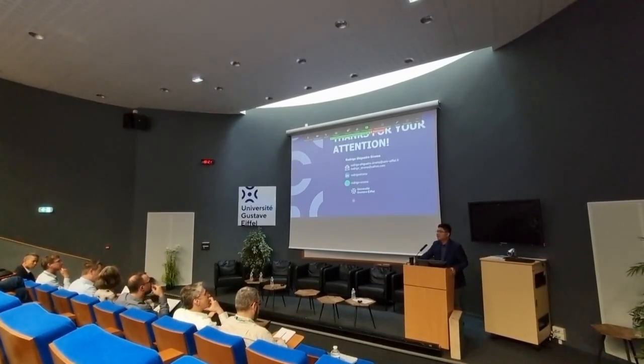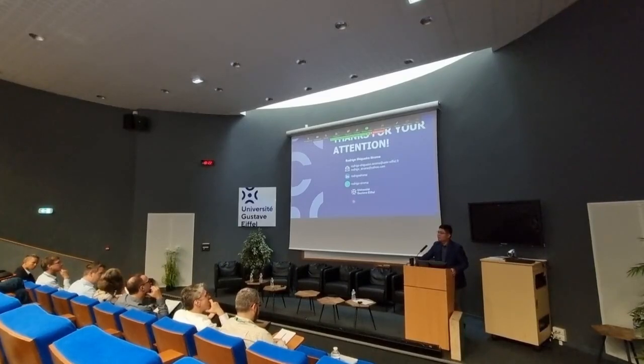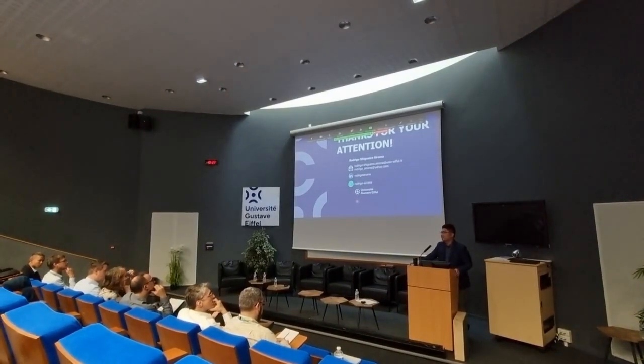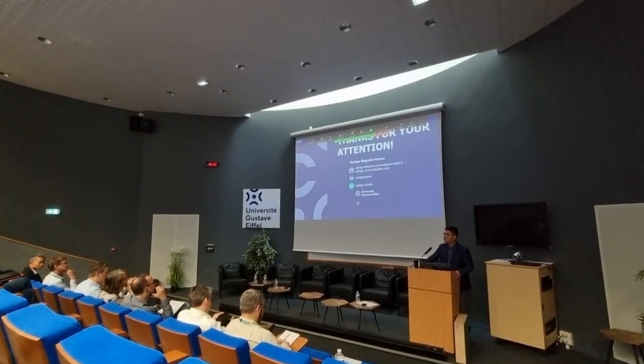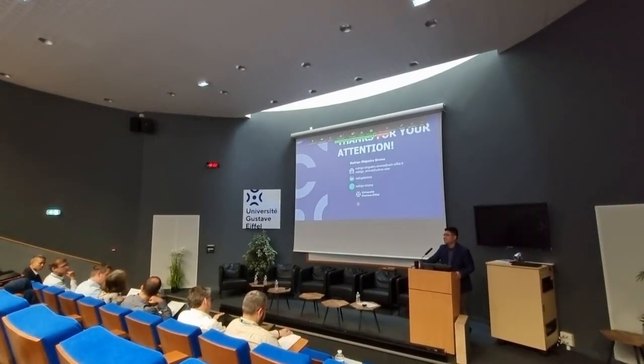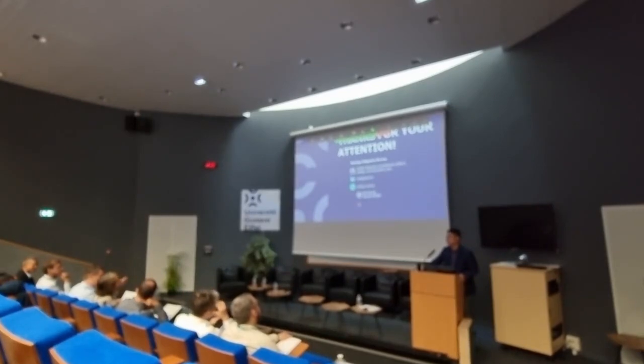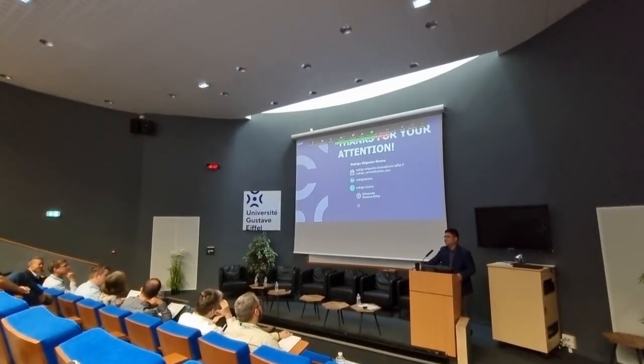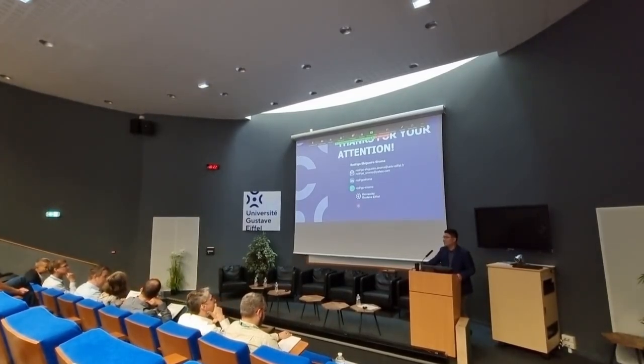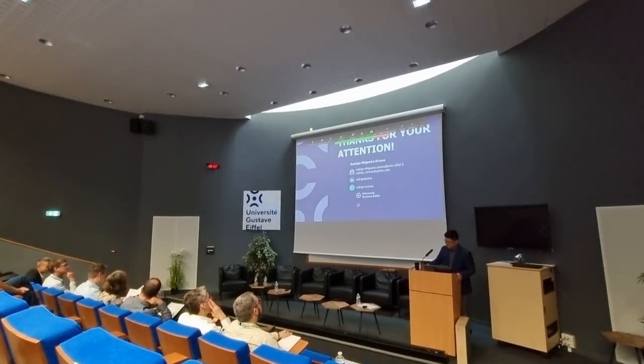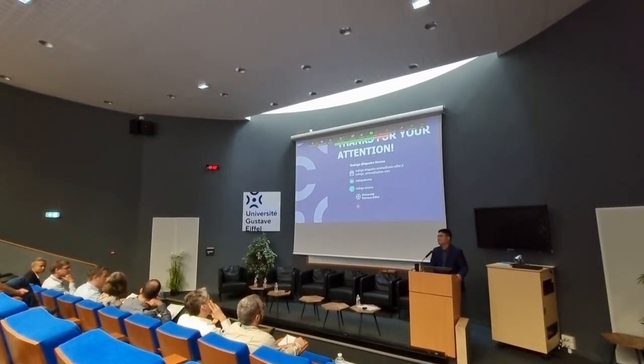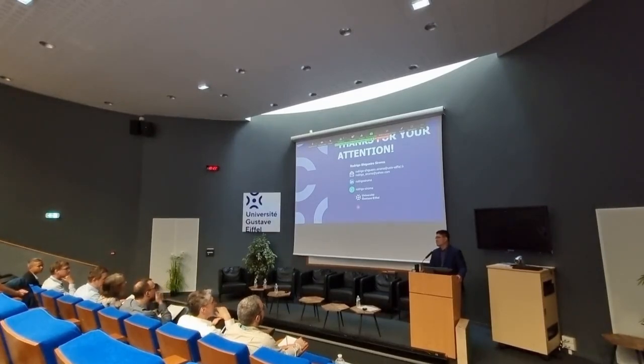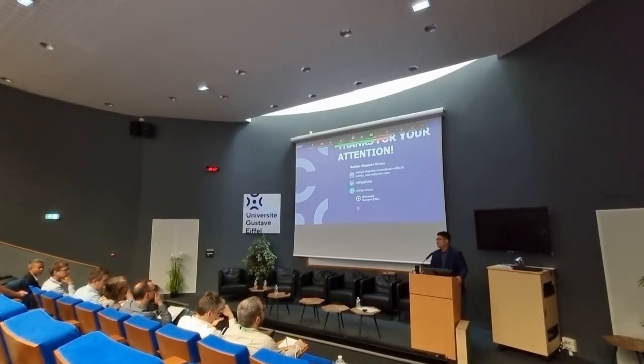Yes. Did you have the chance to try, because I think you said for one of the layers you cut it into two. Yes. Maybe just a comment here, it would be very interesting if you had the chance to cut it even into smaller layers to make sure that this C-shaped curve that you find, which is highly interesting, can be validated. Talking about the C-shaped curve that you found for at least some of your layers, what's your hypothesis? Why do we have higher aging levels on the bottom of the bound layers again compared to the middle?